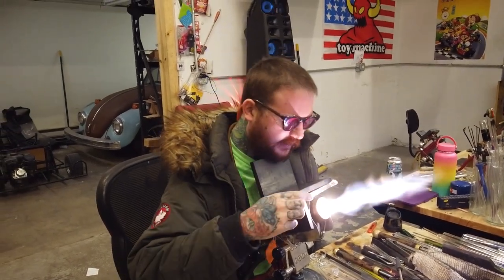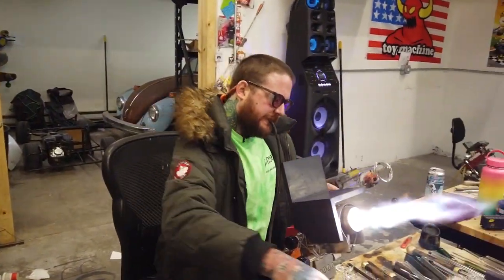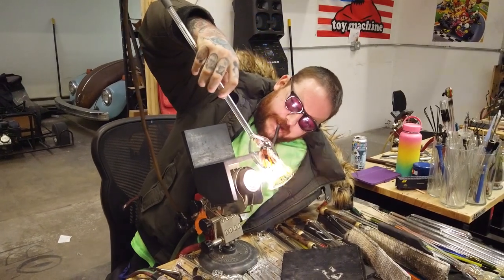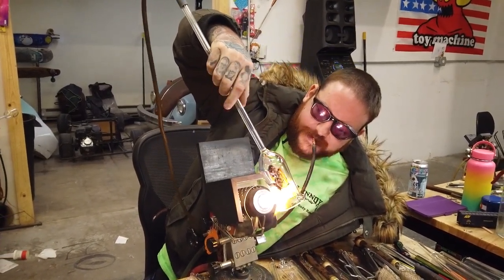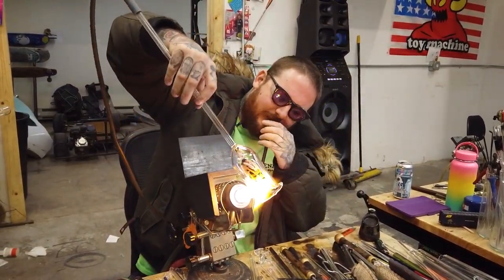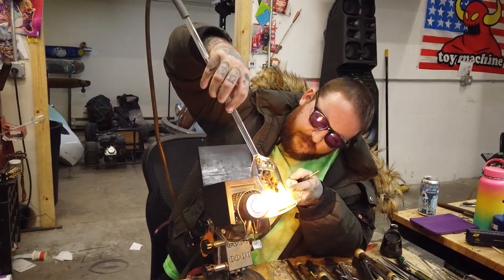Okay, so now you're gonna see why I leave a lot of extra, because the more I put stuff inside things, a ball, a sculpture, whatever you're doing, you wanna try to be able to do it without getting everything hot over and over. So what I do is I heat a ring right here, I just keep spinning it, and I let the ring just drop off, and I flatten the bottom out with the flame instead of the marver, because the marver sucks the heat out of the glass, and you want to try to heat the glass only once right here, because even with these legs and stuff, you don't want his legs to get too hot and start bending. So you can see it starting to pull down already.